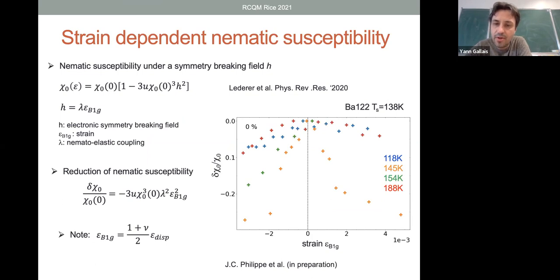So the orange points are the change in nematic susceptibility as a function of both compressive and tensile strain. And the important thing is that you can have a relatively simple expression of this reduction of nematic susceptibility under a symmetry breaking field, and you expect it to essentially scale. This is one of the equations at the bottom, as lambda square and the susceptibility to the cube. And indeed, when you go away from the phase transition temperature, nematic susceptibility decreases and the effect is diminished.